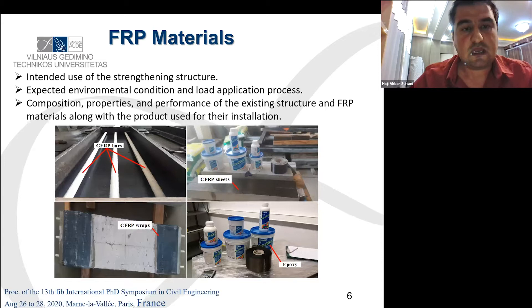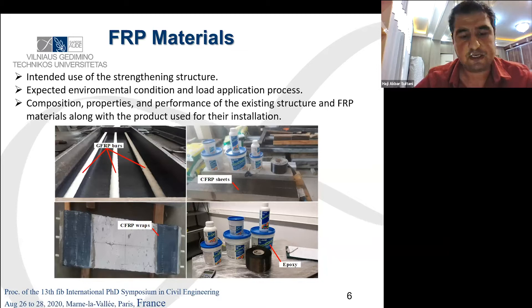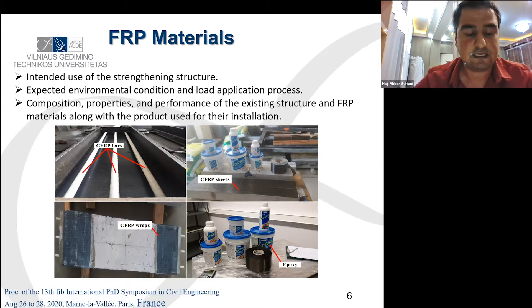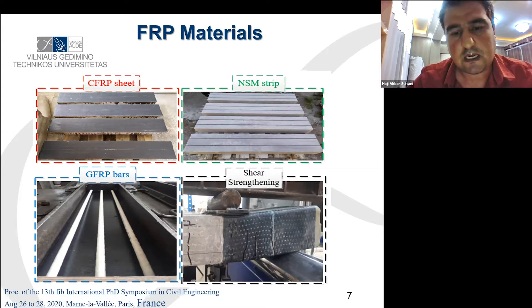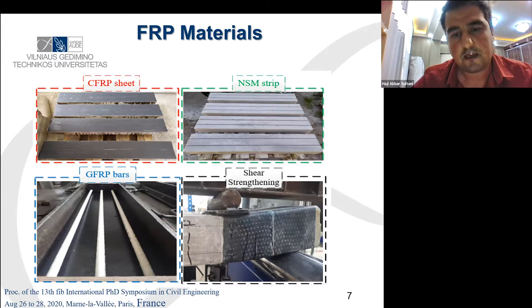FRP material is used as a strong and lightweight composite; this study employs FRP material for strengthening purposes. FRP material is non-corrosive and exhibits high tensile strength, but low resistance in the transverse direction, and relatively small longitudinal modulus of elasticity are the main disadvantages of the CFRP material. Several samples were reinforced using GFRP bars of 13 mm and 16 mm diameter. Many samples also had NSM, near surface mounted, CFRP wrapping in the shear zone to avoid premature failure of the specimens.